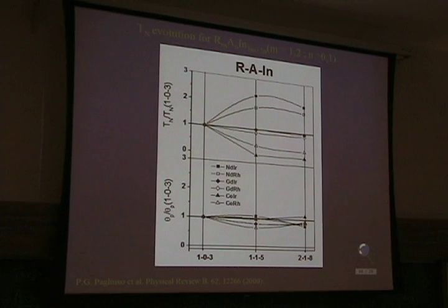They have about the same theta at high temperature, above 200 K. So that tells you that for the cubic compound and both the tetragonal ones, 115 and 218, rhodium, iridium, they have about the same effective magnetic interaction at high temperature.